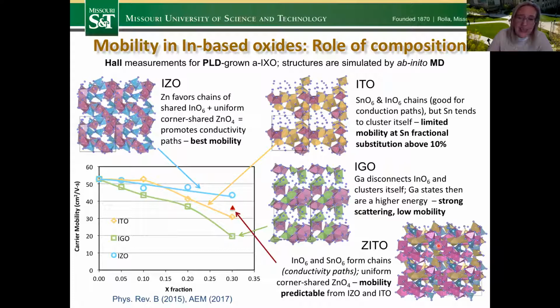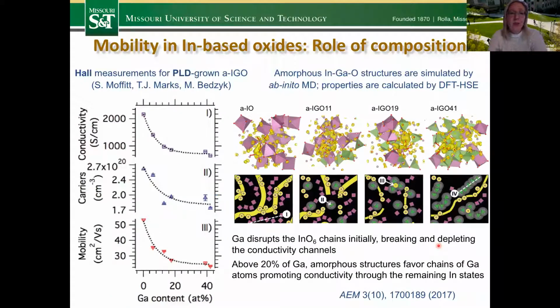Just to take a little bit of a step further, for the indium gallium oxide, we've done a collaborative work, again experimental and theoretical, by looking at even higher gallium content. So before I showed you up to 20 or 30, but now it's up to 40%. And in agreement with the previous slide, the mobility drops down significantly, as well as the carrier concentration, but it saturates, and it's not falling further as we keep increasing the gallium content. So that was very puzzling when the observation was made, why we are not reducing the number of carriers, and the mobility is not reduced as we go beyond some point in gallium content.